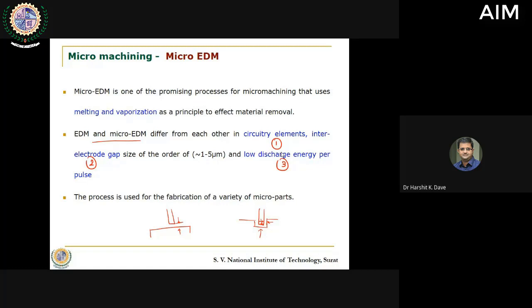Only problem is it is a very slow process, and it is slower than the regular EDM process. If you carry out a task on an EDM process to remove a certain amount of material, or say to reduce a feature by 1/10 of its size, whatever be the feature, the time that you require on an EDM is 1/10 of what you require on a micro EDM. So those simple tasks which I am going to show you would also take around 30 to 40 hours of machining. So that way it is not a suitable process for producing parts in large quantity.